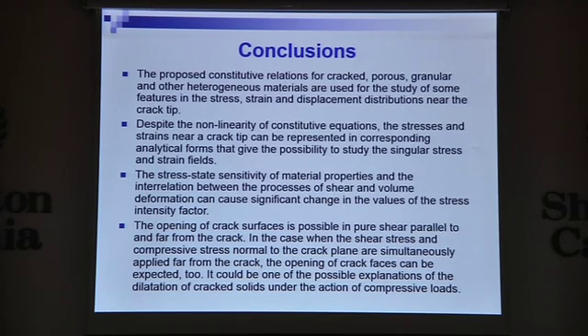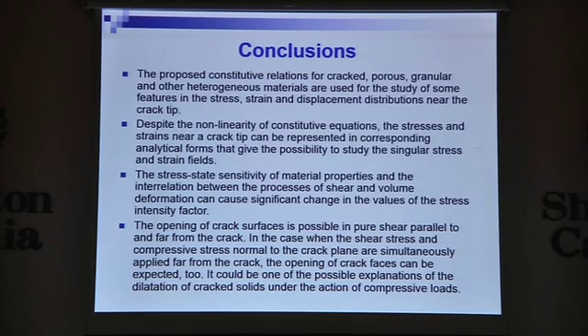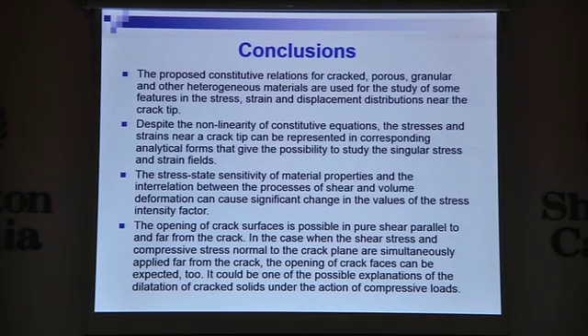I would like to draw your attention to the complexity of solving problems for heterogeneous materials, because the stress-state parameter near the crack tip is not constant. This means that material properties depend on the stress-state type and change from point to point, and we have to take into account this additional heterogeneity of material properties. Another effect is that along each ray originating from the crack tip the parameter is constant, but it has different values for different rays — meaning a primary isotropic material becomes anisotropic. These effects were taken into account when solving the problem. Thank you.